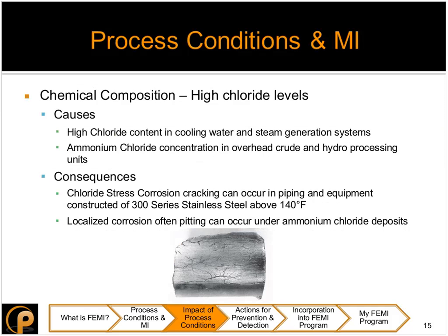Now, going through some of the chemical processes that can cause failures on your equipment. The first scenario is high chloride content in cooling water and steam generation systems, where chlorides can condense and cause chloride stress corrosion cracking in equipment that is made of 300 series stainless steels.